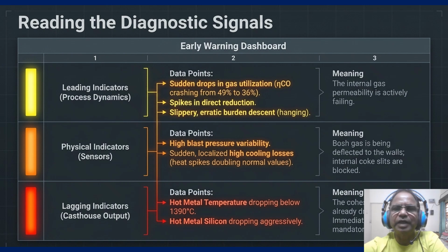So here, when a chilling slip sequence is identified, the first rule is do not force production. You must break the cycle immediately. That is, first, maintain continuous casting to keep liquid level low. High liquid exerts upward buoyancy on the dead man, further compressing the cohesive zone and increasing blast pressure.